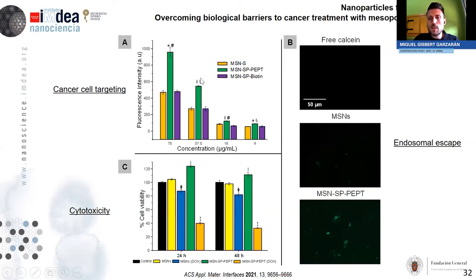Okay, so after that, we tried to check if we could induce the endosomal escape. And for that, we carried out an experiment with calcein. So calcein is a membrane impermeable molecule. So if we add calcein to cells, it won't go into the cells. So we can see here black, so no calcein inside.